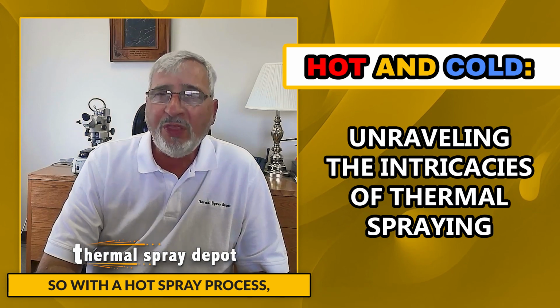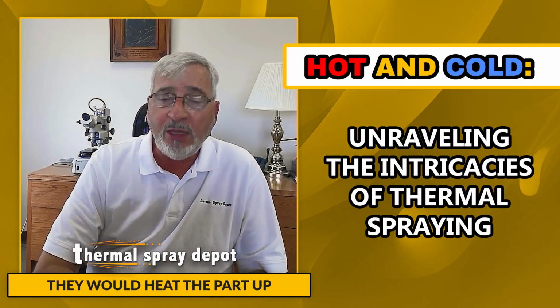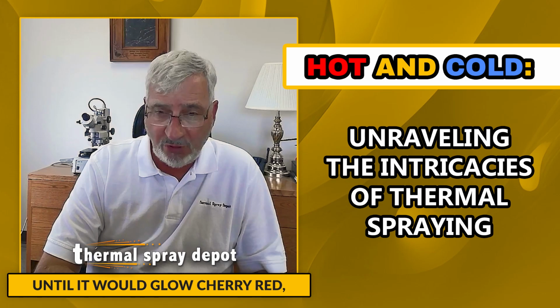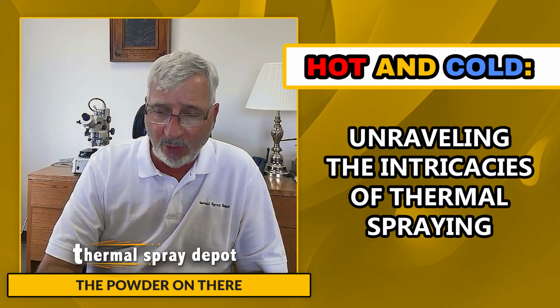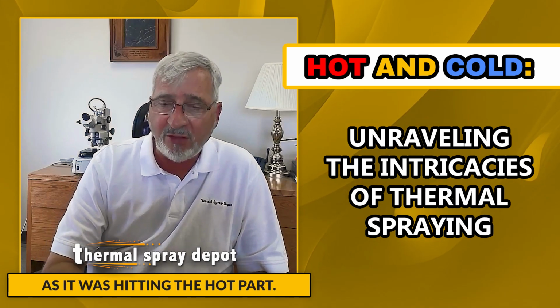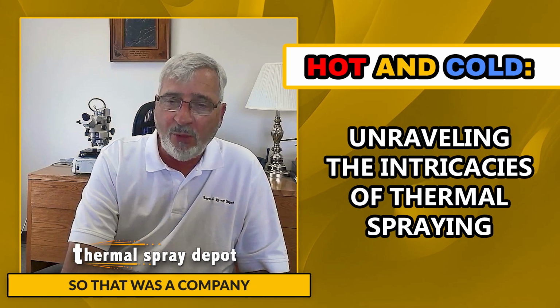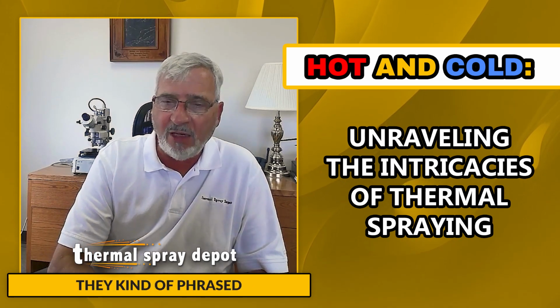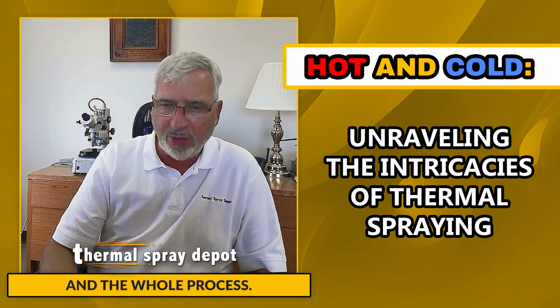With a hot spray process, they would heat the part up to a glowing cherry red, and then they would feed the powder on there and melt it as it was hitting the hot part. That was a company called Eutectic. They kind of phrased it as the hot process and the cold process.